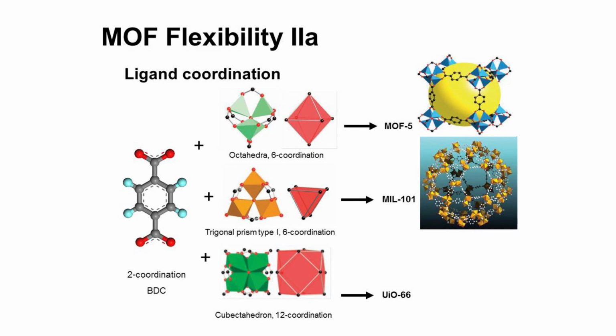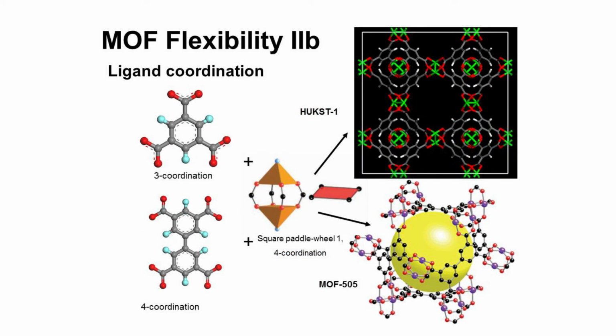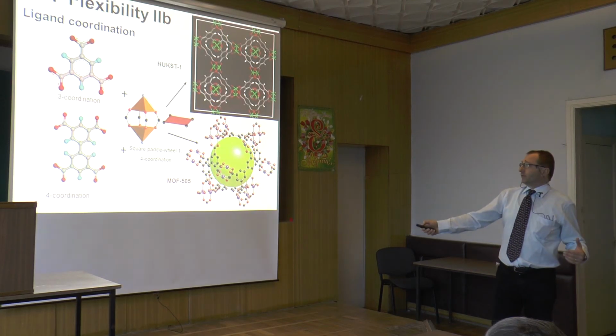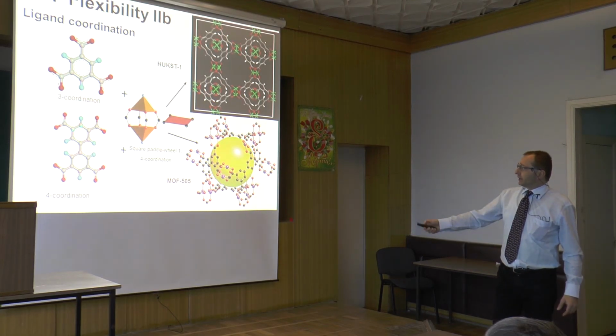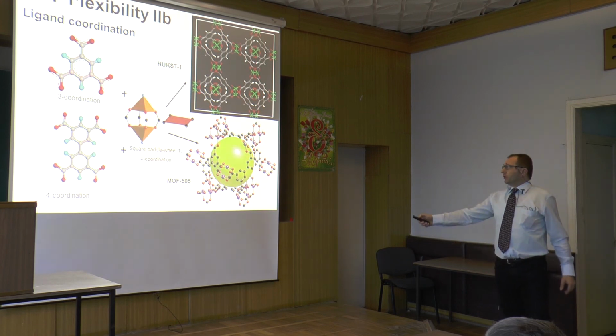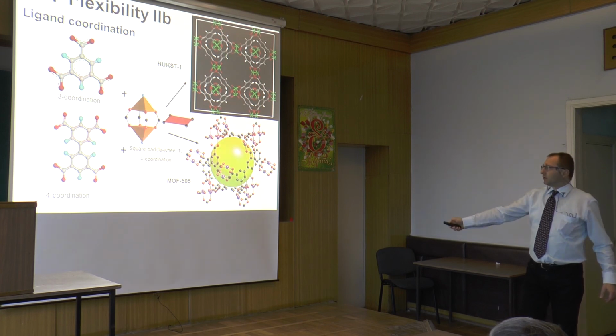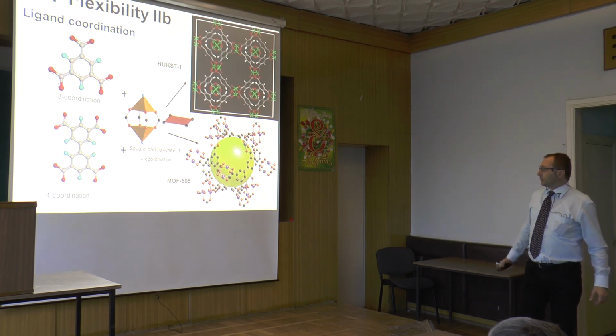Then we have flexibility in the ligand coordination. This is always the same organic linker, and if we choose this cornerstone or that cornerstone, we end up with MOF5, with MIL101, or with UiO66, which are completely different structures. More. Now imagine that we can fix the inorganic cornerstone and change the geometry of the linker. This is a linker with 3 coordination, this is a linker with 4 coordination, and with the 3 coordination we end up with HKUST-1, while with the 4 coordination we end up with MOF 505.